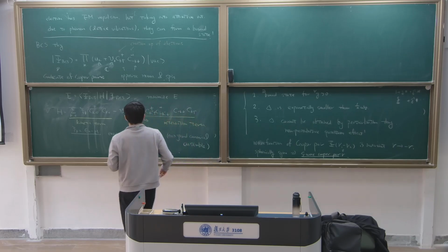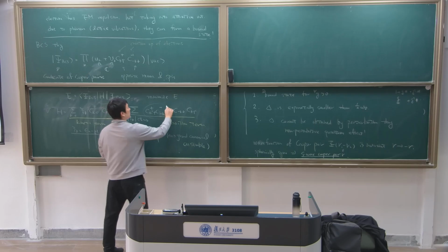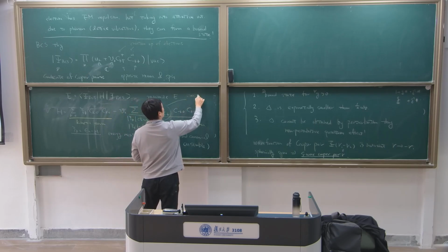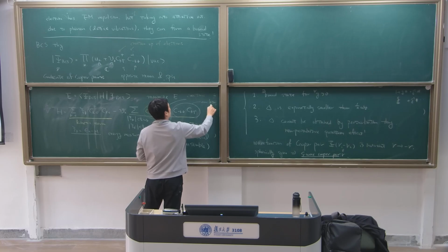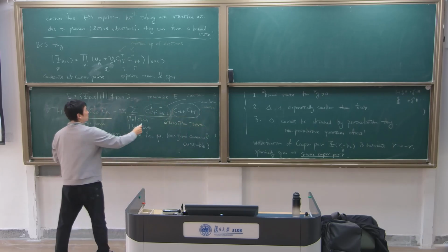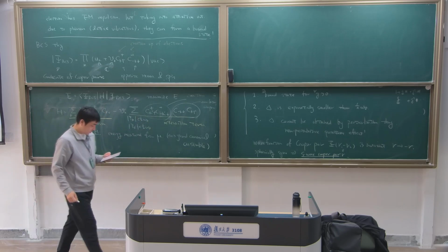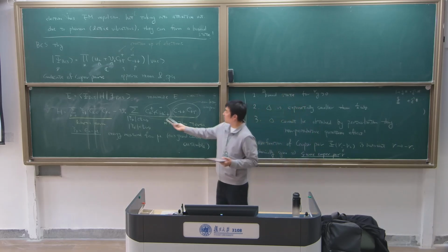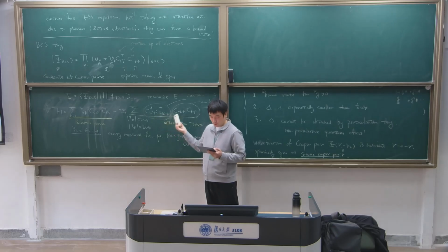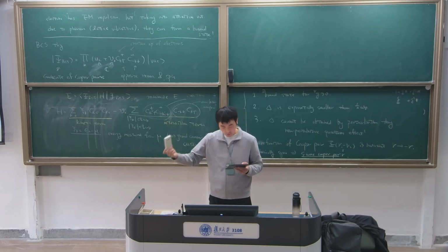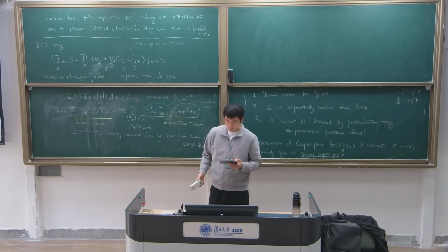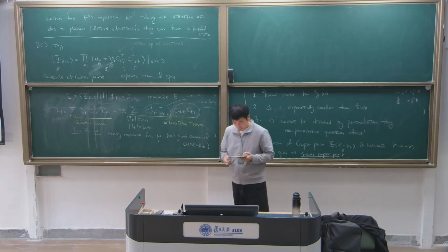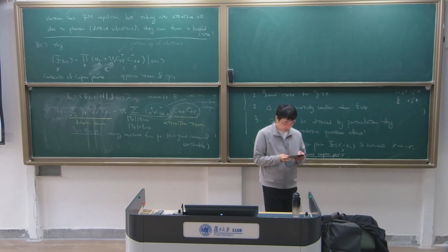Okay, so this interaction is that you create a pair, creation of the pair, and this is annihilation of the pair. And this somehow interacts, that's the BCS interaction. And so this term is for S-wave superconductivity. If you try to consider others, like when it's not spherically symmetric, this term needs to change. But for the sake of simplicity, we only consider the simplest interaction.